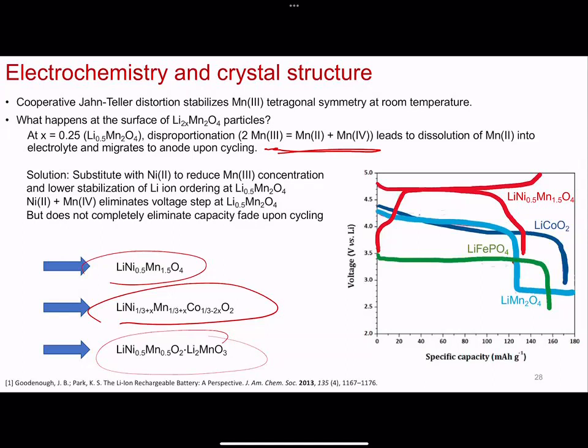With nickel, if you've worked with materials like NMC, right, then the higher nickel content is and has been and continues to be a challenge. So in this particular composition, if nickel, manganese, and cobalt are all the same stoichiometry, we call that the 1-1-1, which would be the colloquial vernacular. But when you increase nickel to something like 622, 811, those are the ratios of nickel to manganese to cobalt, then we start to really have issues with phase stability because nickel at high temperatures is not stable, right?